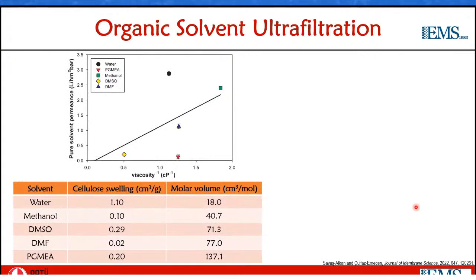However, these membranes or others that can be formed from conversion from cellulose acetates can perform in organic solvent ultrafiltration. This is much less explored than organic solvent nanofiltration, but still has quite a lot of potential applications. So we wanted first to see how these ultrafiltration membranes would perform in different solvents. Water as a reference solvent, dimethyl formamide, dimethyl sulfoxide, methanol, and propylene glycol methyl ether acetate, PGMEA, as a different solvent that we later used in a potential application.